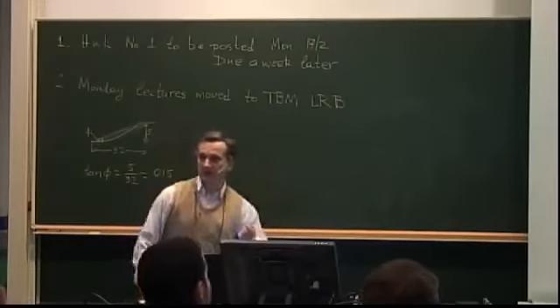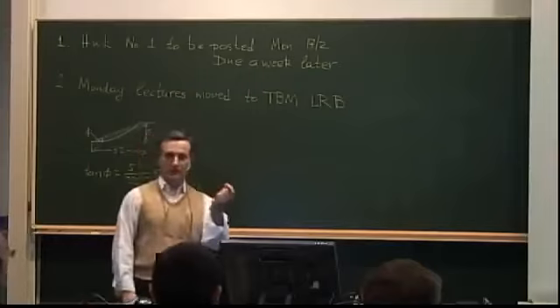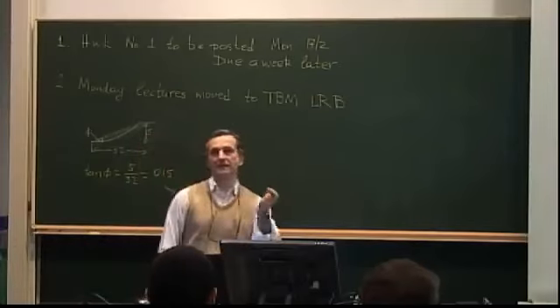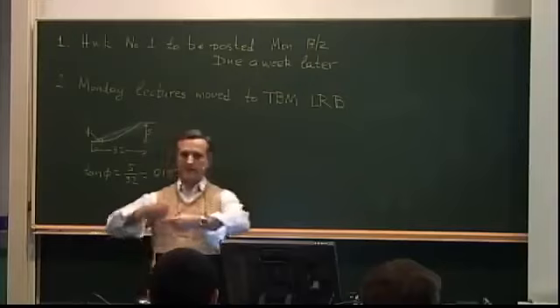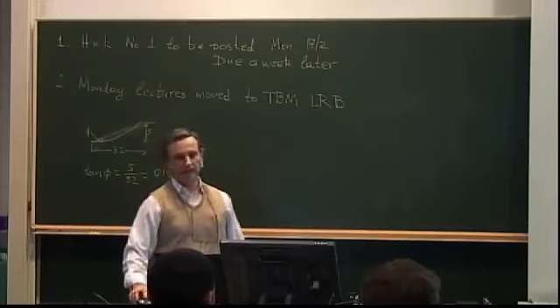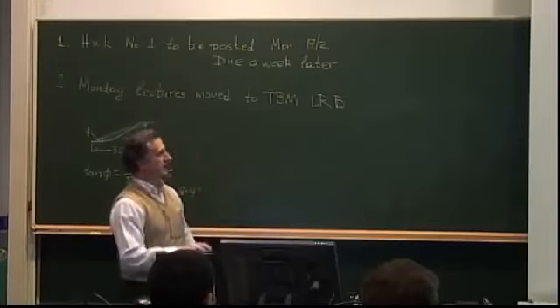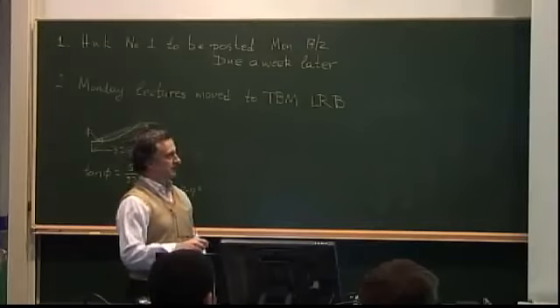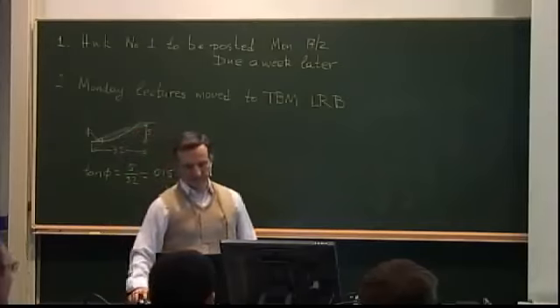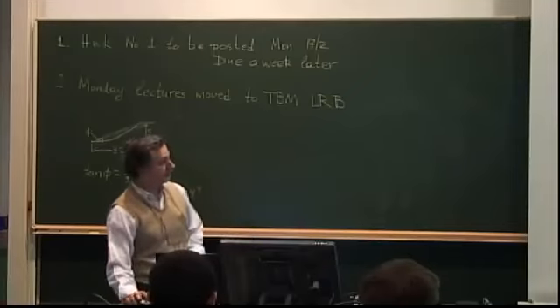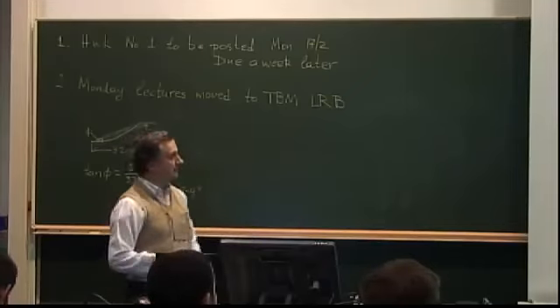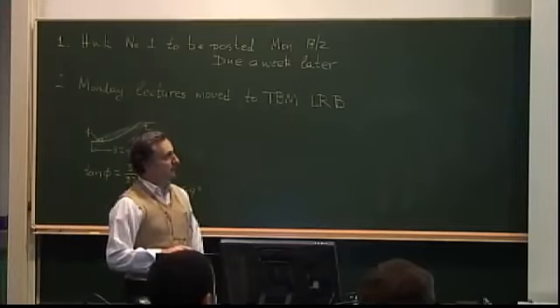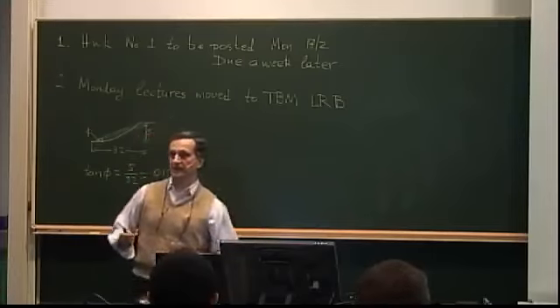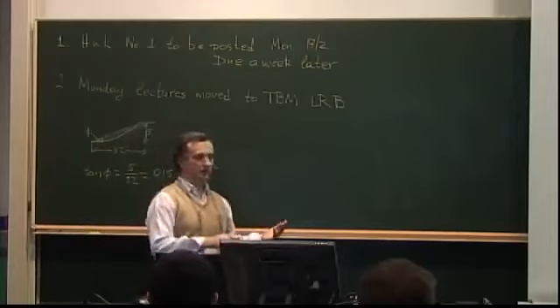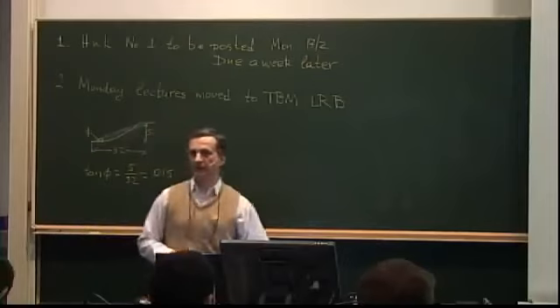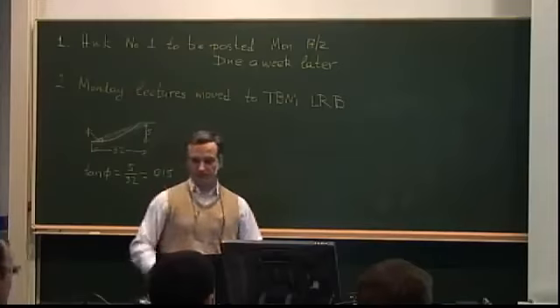Once you start breaking fibers, you have huge stress concentrations at the location where the fibers broke, which means most likely that the matrix now will fail there. So the sequencing of events becomes quite critical after a while. So that's what it looks like. My fibers are horizontally at this picture. The applied load is in tension. Now, you could have tension perpendicular to the fibers, which is this picture at the bottom left, with the fibers again running horizontally. In this case, no matter how you slice it, unless you have fibers in the loading direction, it's the matrix that fails first. Given the fact that it's much weaker, it will fail first.